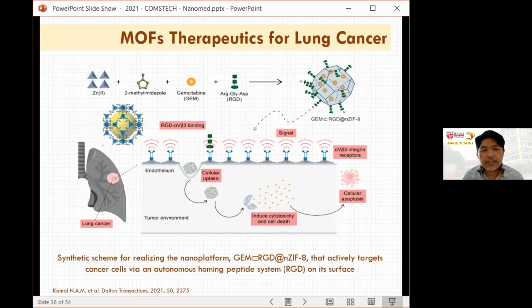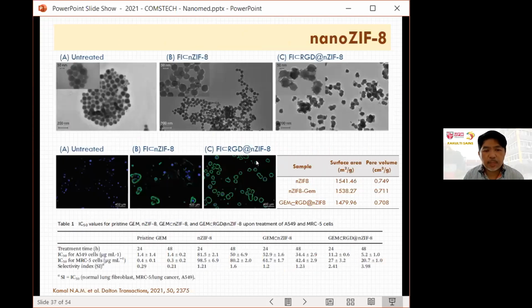In that case, with the RGD-functionalized nano ZIF, we're able to get a very small ZIF, below 100 nanometers, carrying a chemotherapeutic payload, in this case gemcitabine. Then the reticular nanoparticle can dock on the surface of the cell to deliver the agents being carried. Once it reaches the tumoral endothelium surface, cellular uptake will occur, and then the gemcitabine induces cytotoxicity that leads to cell death and ultimately cellular apoptosis. We have shown that the successful functionalization of the surface with RGD was proven by spectroscopic and electron microscopy techniques, but I will not show you all the XRD, FTIR, and so on.